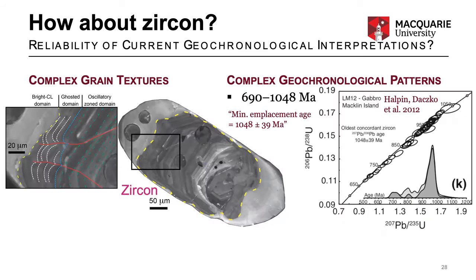Stepping to zircon and the research we've done in the past on the Mawson Charnockite in Antarctica, I showed the complex textures on the left early in the talk and the spread of zircon ages along Concordia over a couple of hundred million years, between 690 and 1048 Ma. Our interpretation when we published it back in 2012 was that around 1050 was probably the emplacement age for the Charnockite, or at least the minimum emplacement age, and everything else in the age pattern was some sort of mysterious lead loss event that we really couldn't get a handle on at the time.